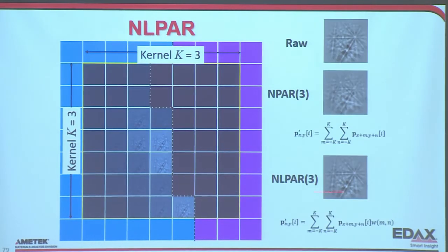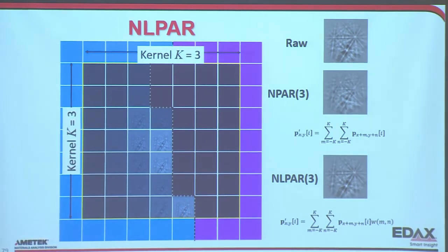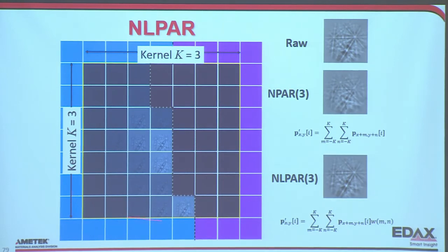If we do NLPAR now and we weight them, then these get weighted towards 0, and the one here will be 1, the one next to it's very similar. Ironically, this one down here is quite similar. It gets weighted high. So what NLPAR does is it gives us an advantage over NPAR: it throws out different patterns, which allows us really to use even a larger kernel. So we get even more averaging.